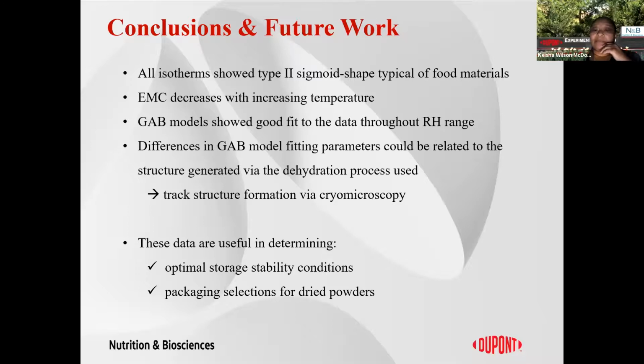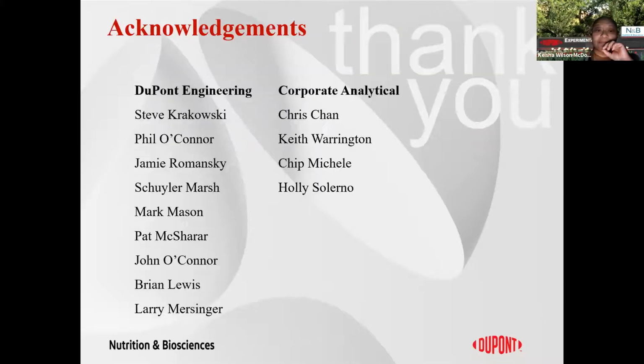The differences in the GAB model fitting parameters could be related to the structural differences we see through the types of particles that we produced via both spray and freeze drying. And one of the things that we might want to look at further is the development of that structure in our freeze drying process, for example, through cryomicroscopy or freeze drying microscopy. Finally, we can use these data to help determine optimal storage conditions, because we now know how the material will perform in different humidity levels. And we can use the isotherm data to define appropriate packaging for materials that are of interest to us.